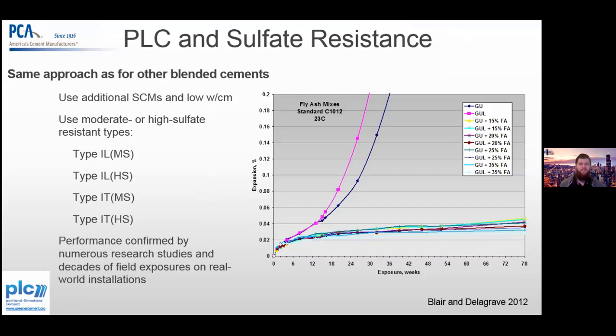It says PLC and sulfate resistance. Oh, sulfate resistance. There you go. That makes perfect sense, because typically, and I showed that already with sulfate resistance, if you put any sort of mortar bars or paste bars into a sodium sulfate solution, it's going to skyrocket. They typically do take off, whether it's Portland cement or Portland limestone cement. But once you start adding supplementary cementitious materials that consume the calcium hydroxide in pore solution, it flatlines and you get below the maximum required to demonstrate that it's resistant to sulfates. That was the reason why Doug wanted the field site in the first place, to demonstrate that. His big concern was sulfate performance and sulfate resistance.